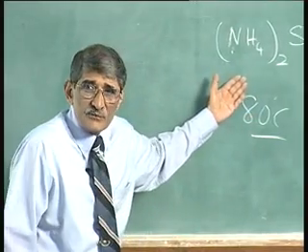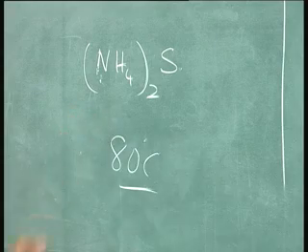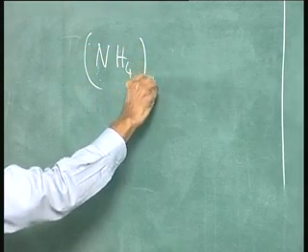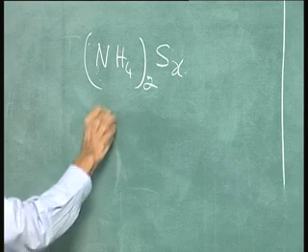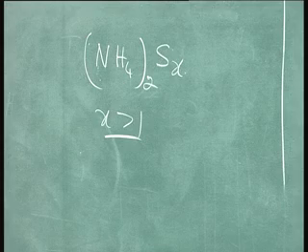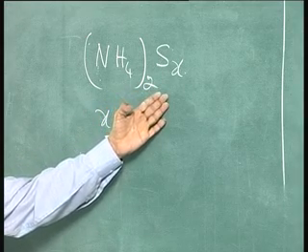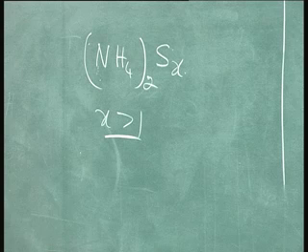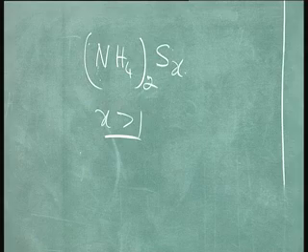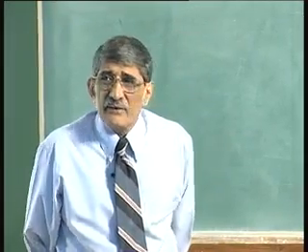In fact, you can buy this type of solution. Ammonium sulphide is available in the market. So, the next level is ammonium sulphide (NH4)2Sx, where x is greater than 1. This is called ammonium sulphide solution which is rich in sulfur. A sulfur-rich ammonium sulphide, x is not 1, x is greater than 1. Okay. There are a lot of reports which came around in the 90s, which said that if you use ammonium sulphide with x greater than 1, up to 2, in that range, you can buy the solution.